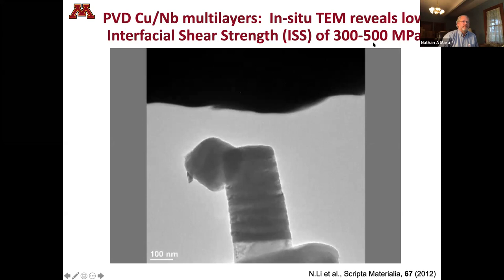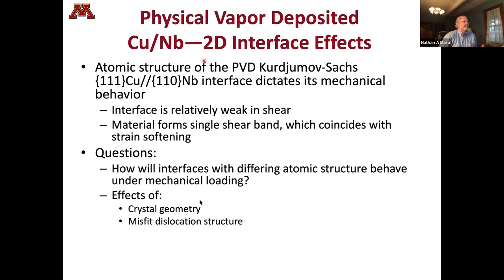It's about 300 to 500 MPa. When we're thinking about the overall strength of that material, when we were compressing perpendicular to those layers before those interfaces rotate, you're talking about stresses that are many times that, about 3 to 4 times that. And so the question is now, how does this actually compare to some of these other materials that we've done?